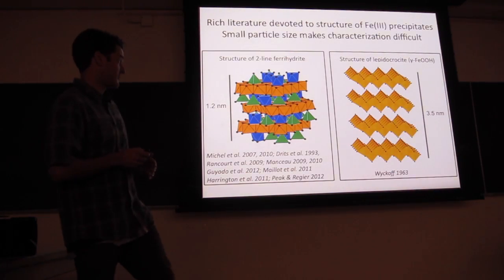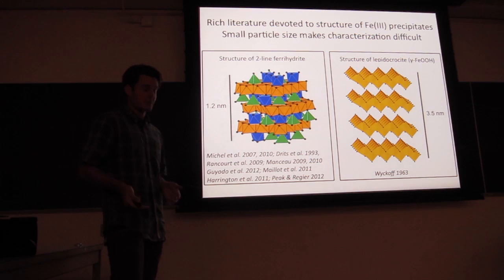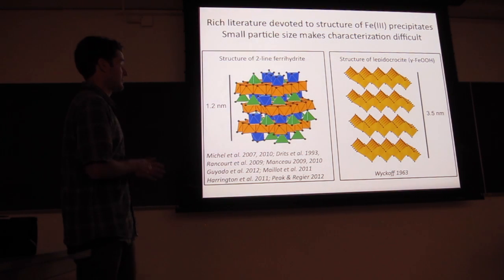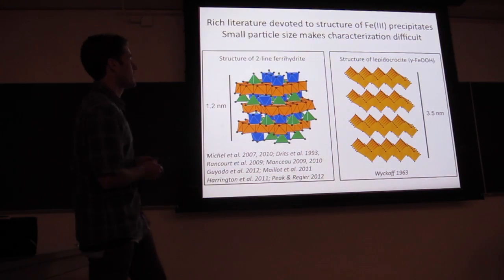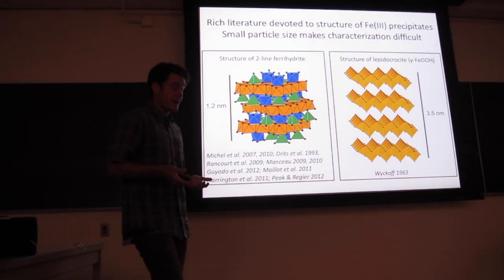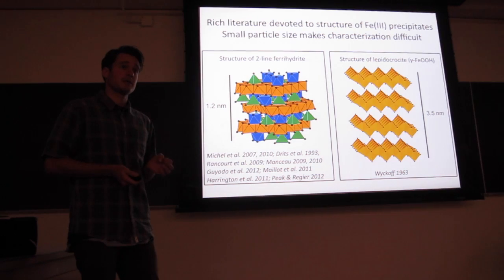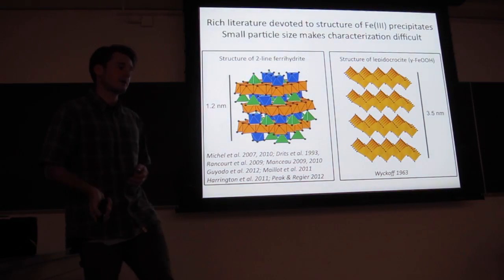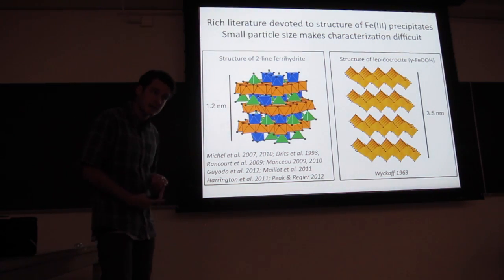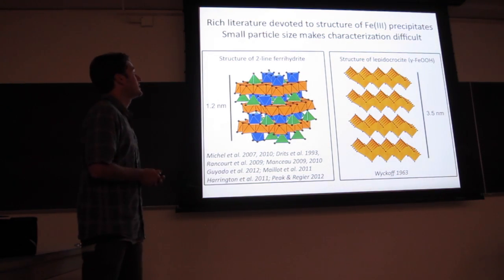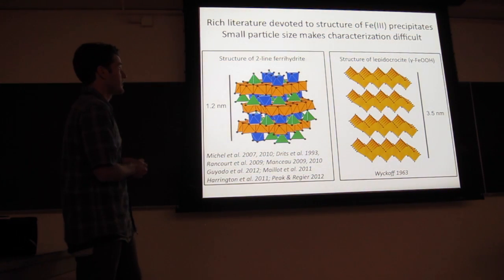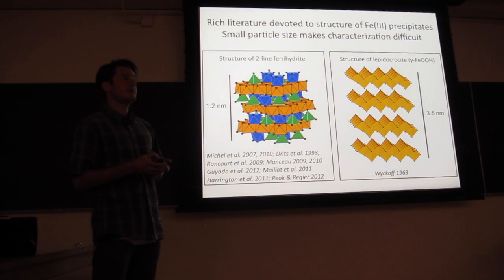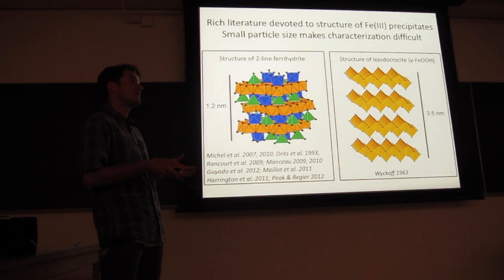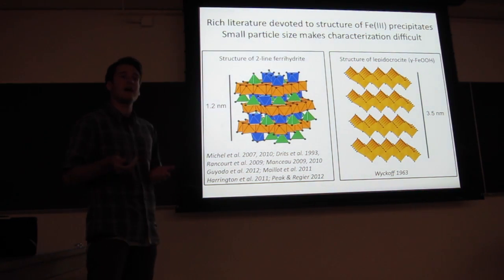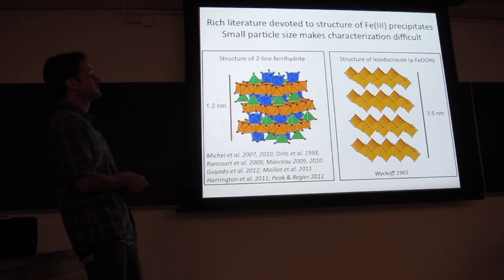Okay, so before I get into the molecular scale approaches that I'm using, I wanted to talk a little bit about iron oxides in general. One of the reasons that iron oxides are so reactive is because they have a very small particle size, but that makes them notoriously difficult to characterize using traditional approaches like X-ray diffraction or electron microscopy. So 2-line ferrihydrite is a reference mineral that people use a lot to model nanoparticulate iron oxyhydroxides, and it's been the subject of considerable research.